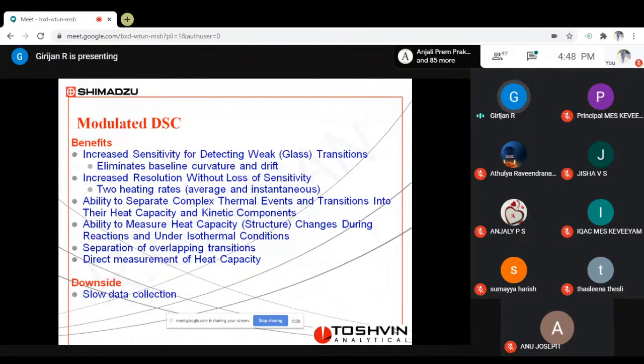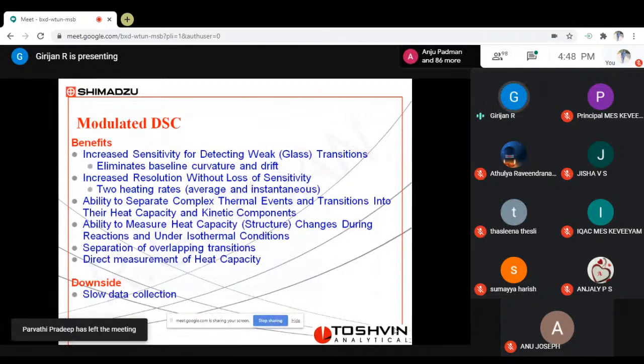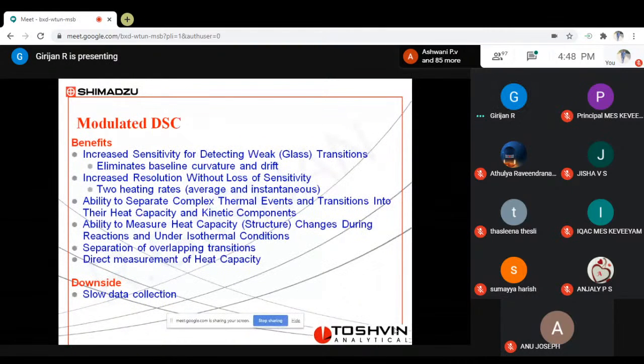The ability to measure heat capacity and structure changes during reactions and under isothermal conditions. Separation of overlapping transitions. We have seen an example, Tg and enthalpy relaxation. In normal DSC, you'll get a single curve because it is an overlapping transition. But when you are using MDSC, you can bifurcate it and get two different signals, one for Tg and one for enthalpy relaxation.